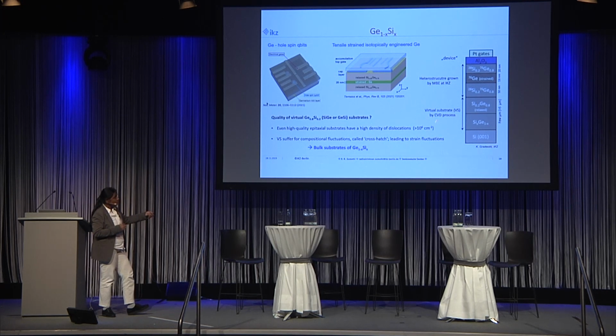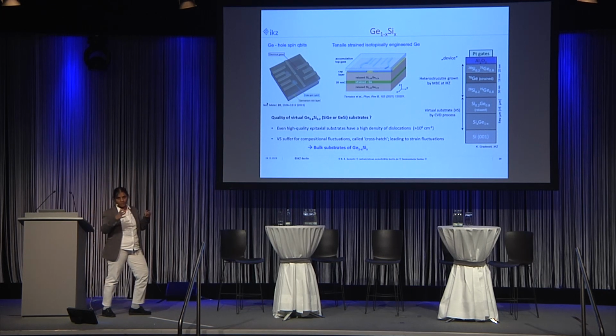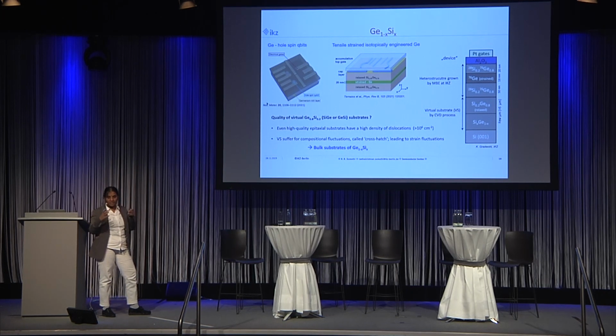So here what you see is the virtual substrate of silicon germanium alloy system, and this has been grown on silicon. There is a very big lattice mismatch between silicon germanium and silicon, and this creates a lot of dislocations in the epi layers, and this is a problem for the devices. For example, if you have compositional fluctuations, then this will also affect the strain in the germanium layer, the fluctuation of the strain.